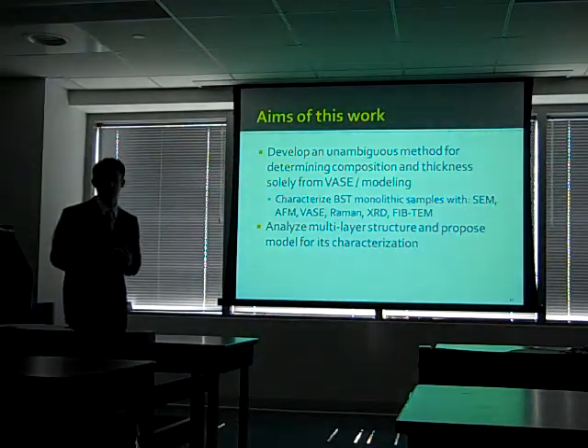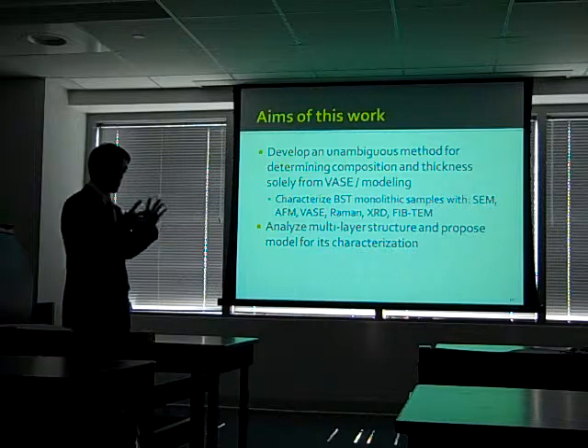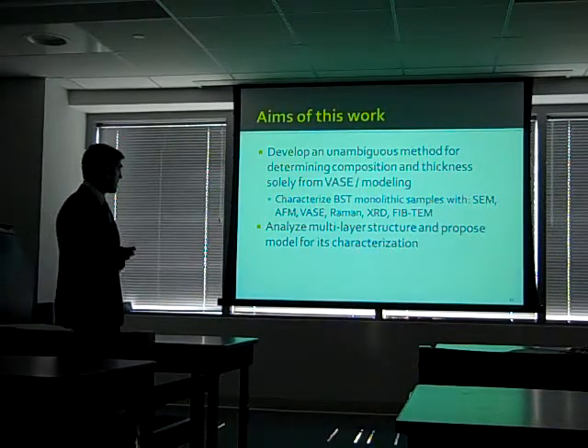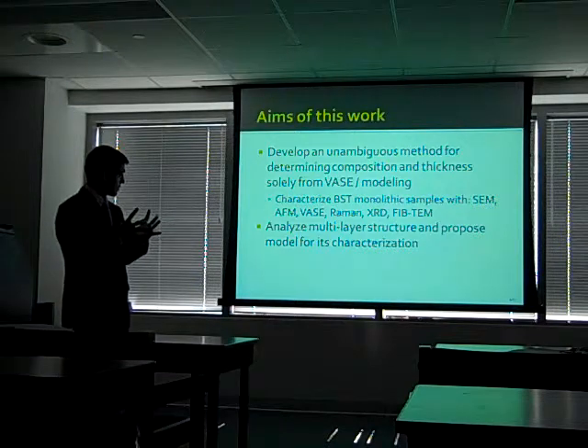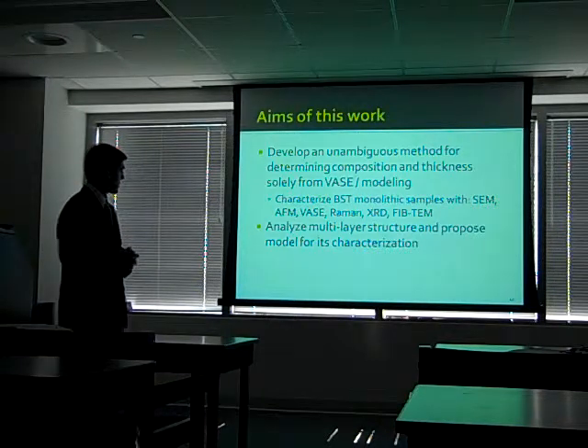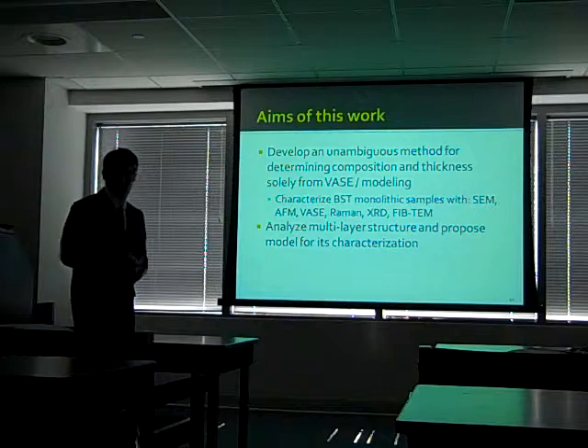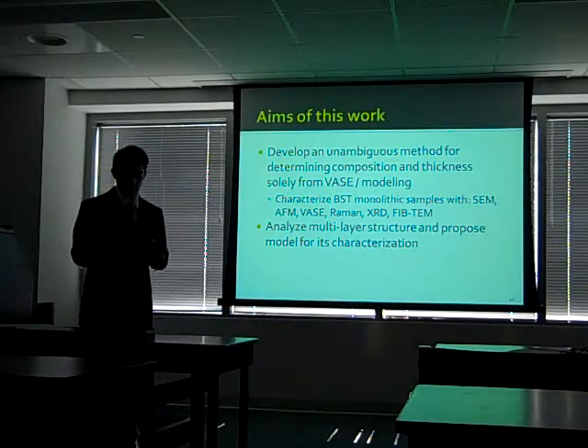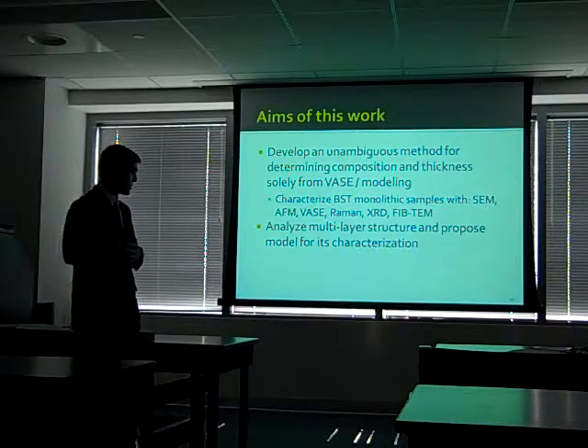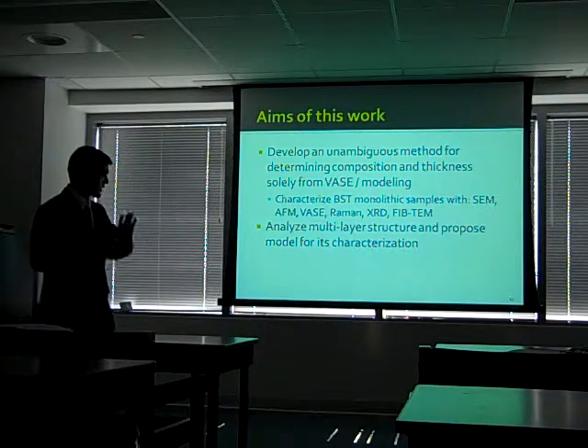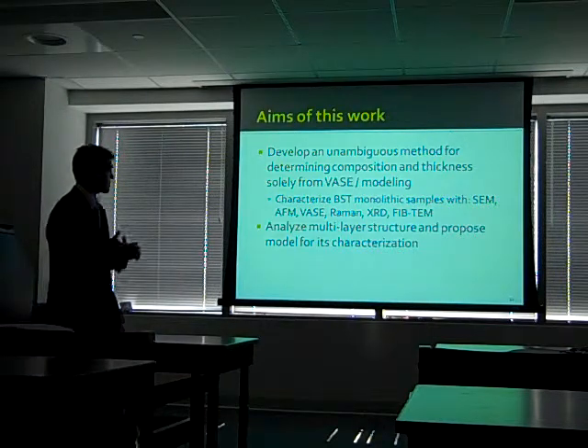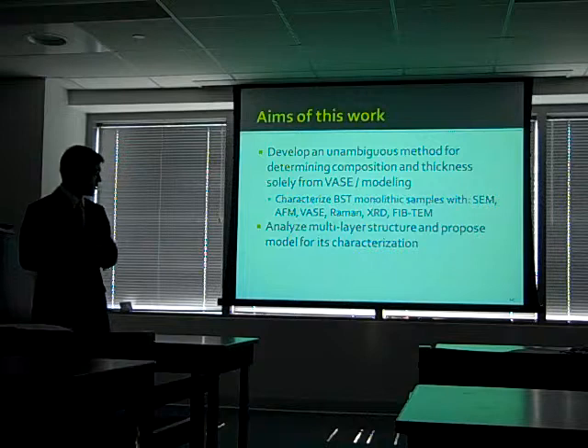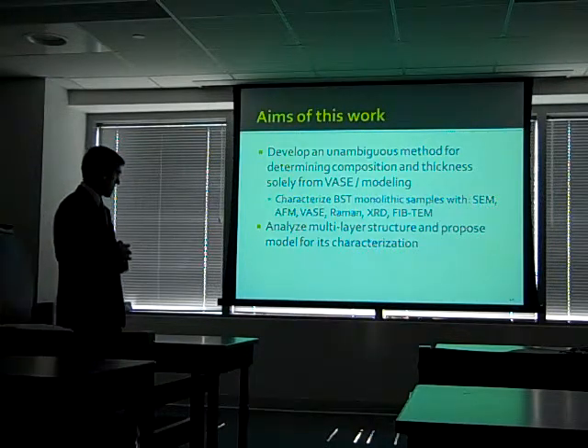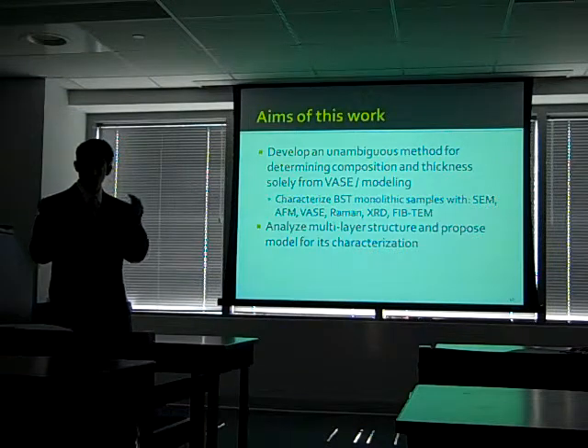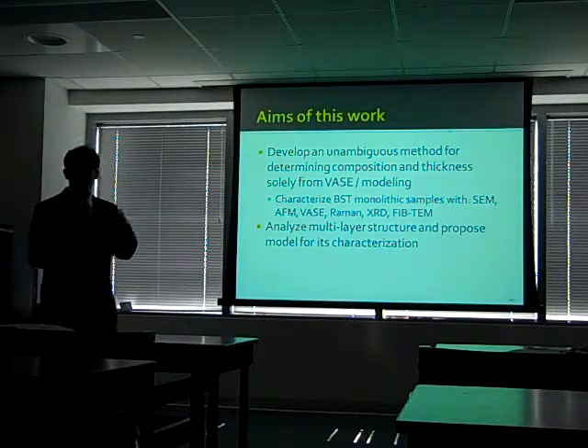So the aim of this work then is to develop a framework to use variable angle spectroscopic ellipsometry, or VASE, as this technique which will provide this all-in-one characterization for these films. And the way that I go about doing that is first by developing an unambiguous method or set of steps to determine composition and thickness from these films. And first, to do that, I'll need to characterize BST monolithic samples with scanning electron microscope, atomic force microscopy, VASE, Raman spectroscopy, X-ray diffraction, and FIB and TEM. And finally, I'm going to analyze the multi-layer graded structure and propose a model for its characterization.